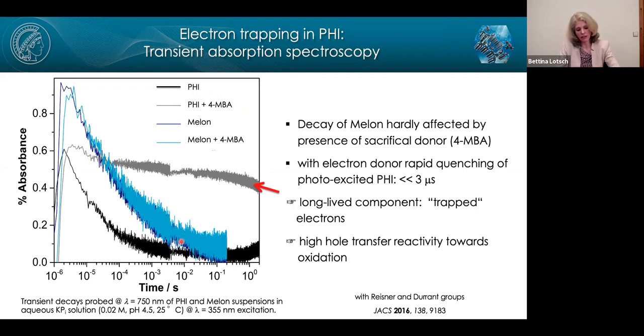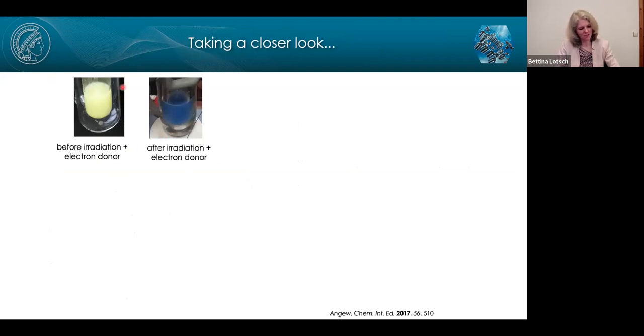Now, we see that the intrinsic decay of Melon and PHI is very similar. But this changes a lot when we add the sacrificial electron donor, because then we see a very long-lived component coming up here for PHI. And this spectral component is consistent with trapped electrons. That is a very well-known signature of trapped electrons on the carbon nitride backbone. And that tells us that the hole transfer reactivity, so the hole extraction in the system, is extremely fast. Holes are extracted very easily, and that is due to the fact that the system has a very low-lying valence band, so it's very oxidative. It oxidizes the electron donor very easily, and the photoexcited electrons are trapped on the system, and we can actually see these electrons with the eye, basically. So here you can see the suspension of the carbon nitride.